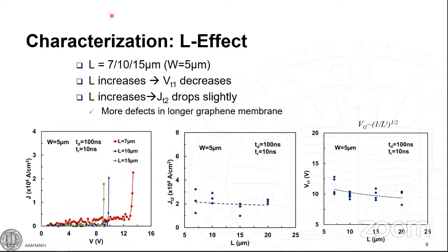Okay, so a little further characterization. We tried all the different dimensions. You see the current handling capability versus the graphene ribbon length, and also trigger voltage versus the length. As the graphene length increases, the trigger voltage decreases a little bit because it's kind of lossy over there. And we did not expect the current density to change. However, we did measure that. That was probably because the graphene film that we use is not perfect.